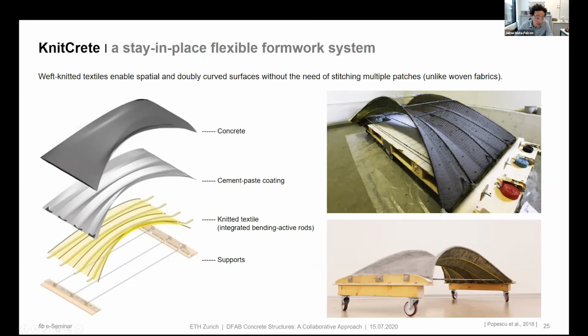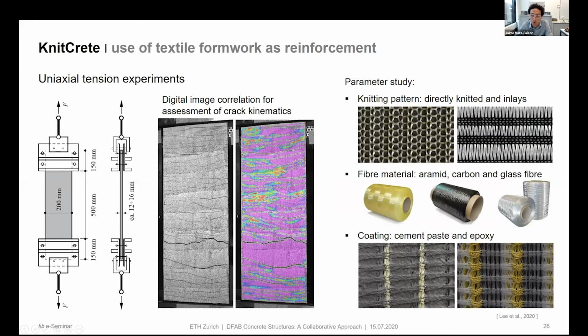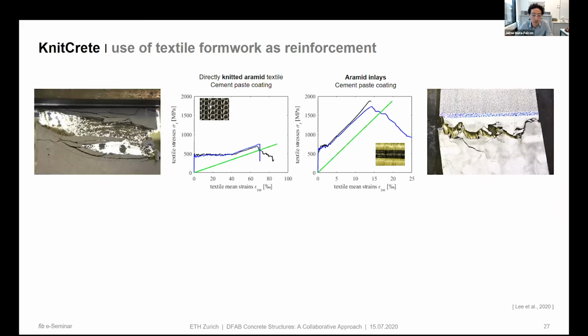And this is the KnitCrete technology, where we have this knitted textile that is tensioned, then cement paste coating is applied to have enough stiffness to cast concrete on top. And now we are working so that this knitted textile is not only lost formwork, but also works as reinforcement, using high strength fibers like aramid, carbon and glass fibers. So we are testing this with direct tension, you see here on the left, and also with bending tests. Here you can very quickly see the results.